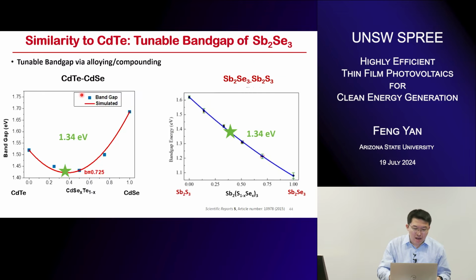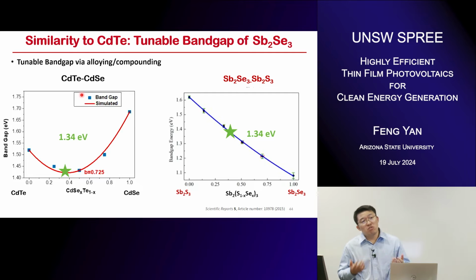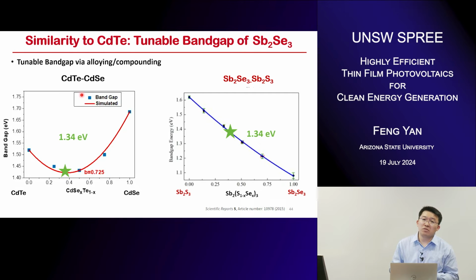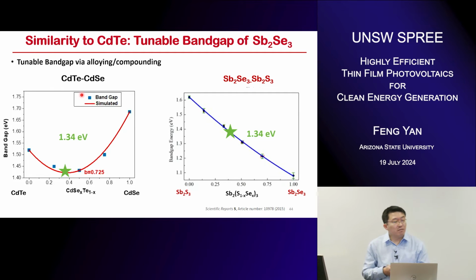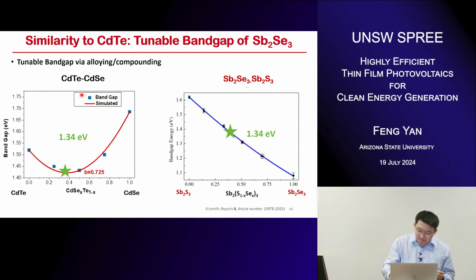Another thing is that it also has a tunable band gap like the cadmium telluride. We introduced different types of gradient absorber in the cadmium telluride, like coupling with the cadmium sulfide or the cadmium selenide. Similarly, for the antimony selenide, the band gap can also be tuned to absorb more or less light. So with all of these similarities, this is why we initiated this project roughly 5 or 6 years ago, using the close-spaced sublimation technique for this material.